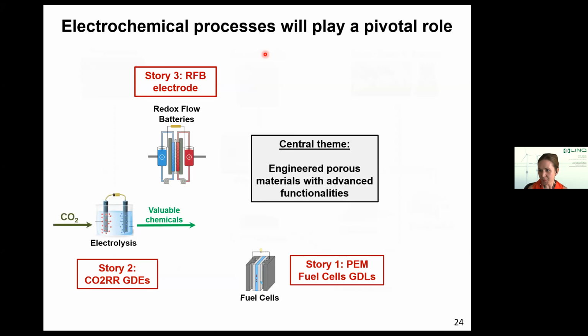The question says, I would like to know how accurately it is possible to calculate the current density in woven electrodes. I guess, how accurately can you calculate the current density? I don't know exactly what you refer to, so perhaps you can clarify. But experimentally, we measure the total current and typically divide it by the geometric area. We also indirectly measure the electrochemically active surface area by doing double layer capacitance measurements. That's our experimental way to determine it. Theoretically, that is harder. In that particular work, we used tomographic microscopy to reconstruct the images and geometrically calculate the surface area. But that has a downside: the minimum resolution of the machine is about 0.3 microns, so there would always be an under-prediction of the surface area.